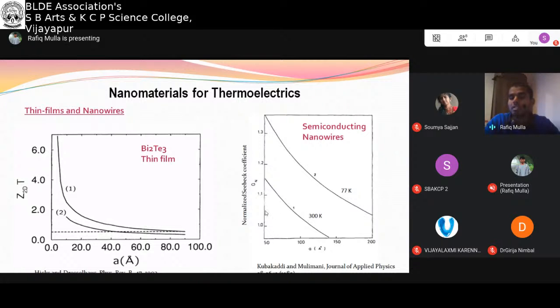The Seebeck coefficient, this is the normalized Seebeck coefficient, so it is here. But as we reduce the dimension, we can achieve a very high Seebeck coefficient. That is almost like 1.3, more than 1.3 times larger than this value. So the Seebeck coefficient can be improved in nanowires, and the ZT value can also be improved both in thin films as well as in nanowires.